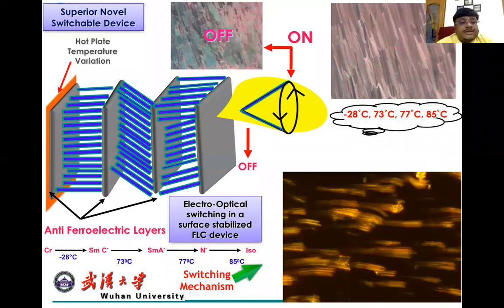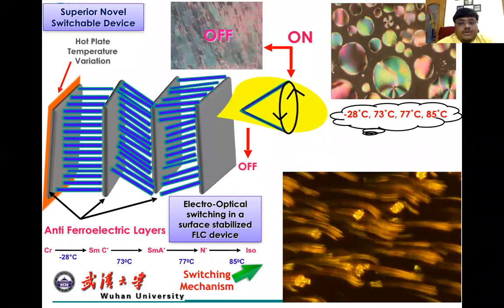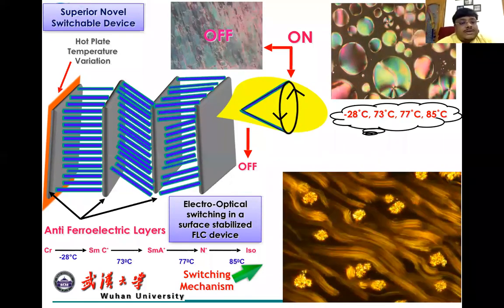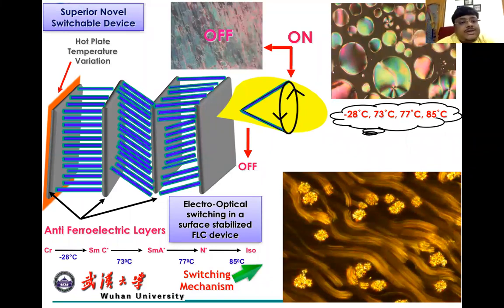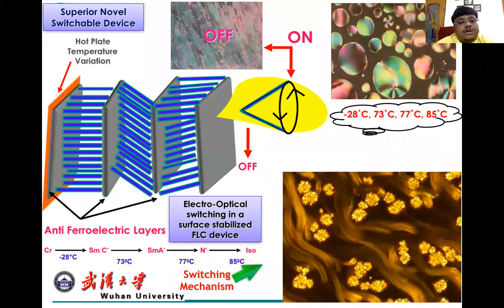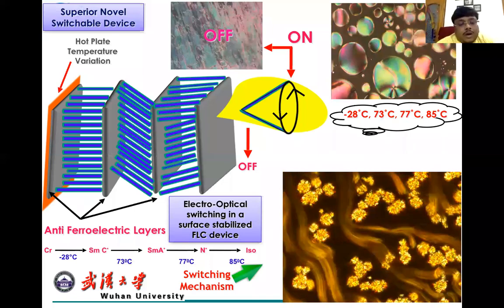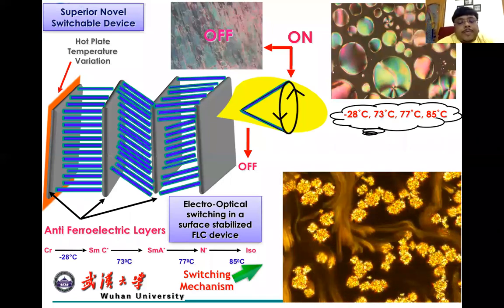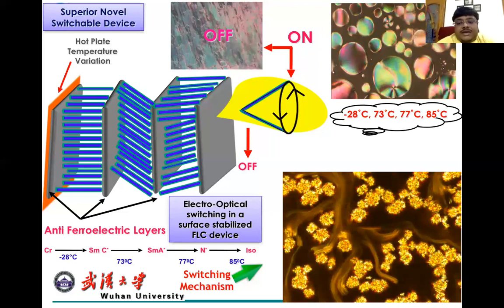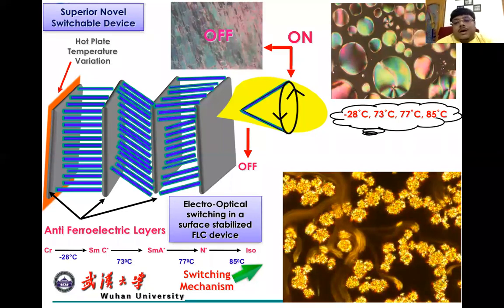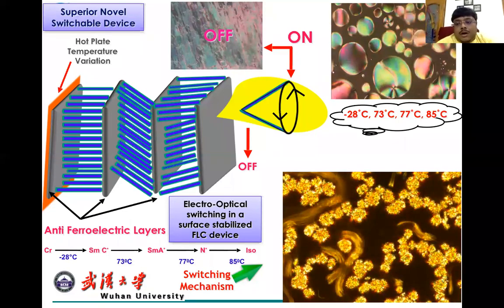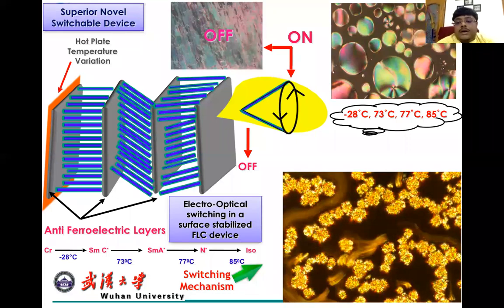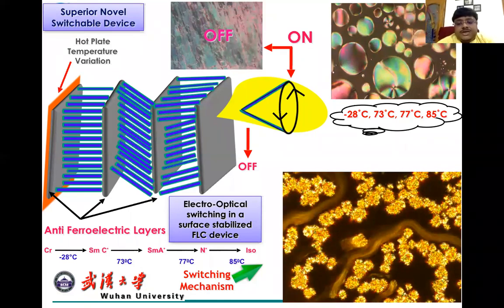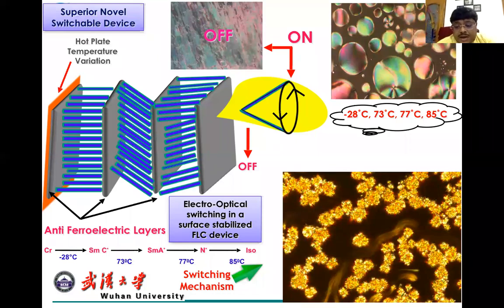And this is the switchable device, the fundamental topic which I'm talking about. You can see here is a hot plate, and the liquid crystal molecule is vibrating when we apply external heat, and on and off states are coming. With different temperatures you can see some droplet-like structures, and sometimes a continuous pattern of liquid crystals simultaneously changes. And you can see here in the video this capillary action inside the geometry.